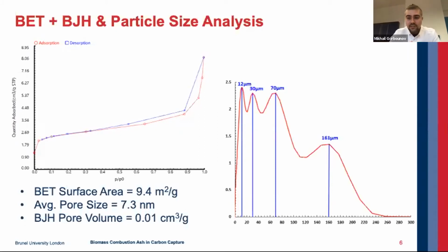And the difference between the adsorption and the desorption pattern is clearly visible on the left part of the slide. If we talk about the particle size distribution of the adsorbent, we will see that the most prominent peaks identified were at 12 micrometers, 30 micrometers, 70, and 161. The presence of 4 peaks suggests 2 different theories. The first approach is based on the presence of the spherical particles, as seen in the SEM imaging. Following this logic, we can assume that the identified peaks correlate with the diameters of the round particles found within the fly ash. So this assumption is confirmed by a visual examination of the SEM.